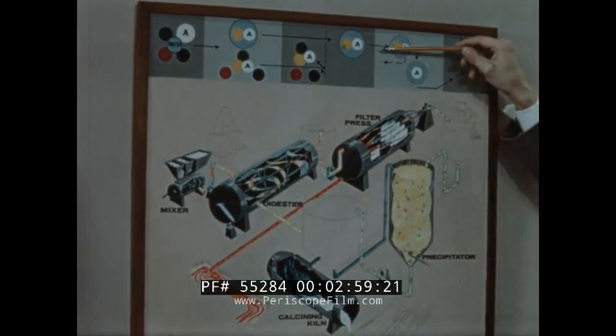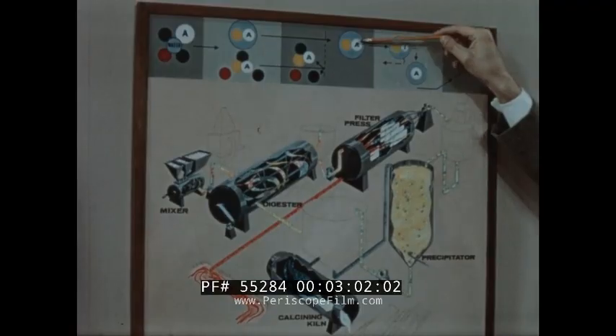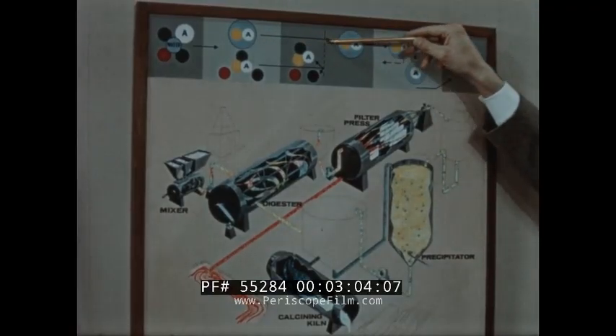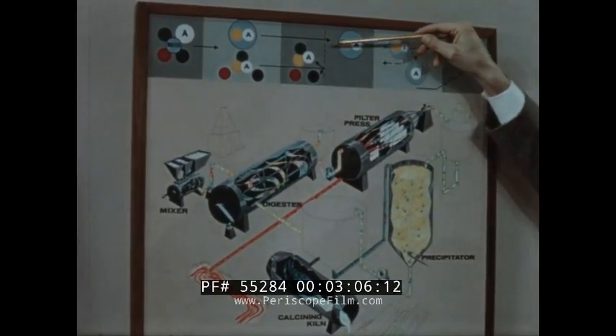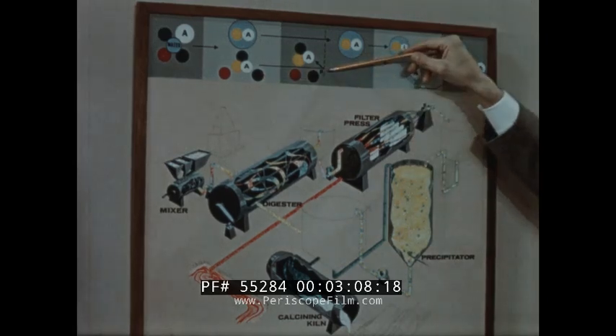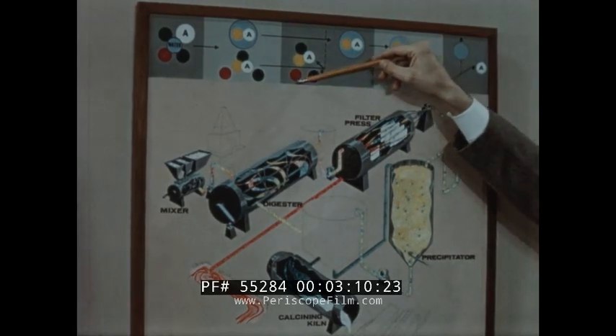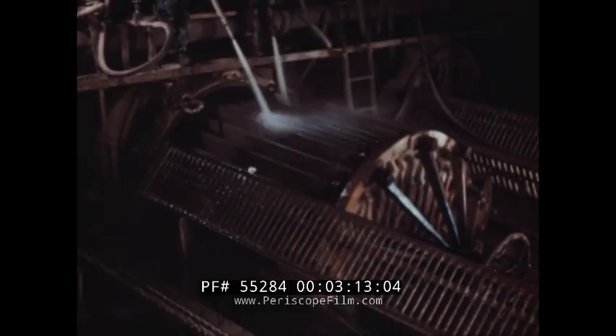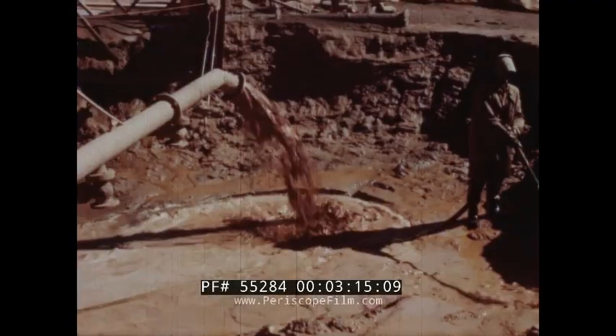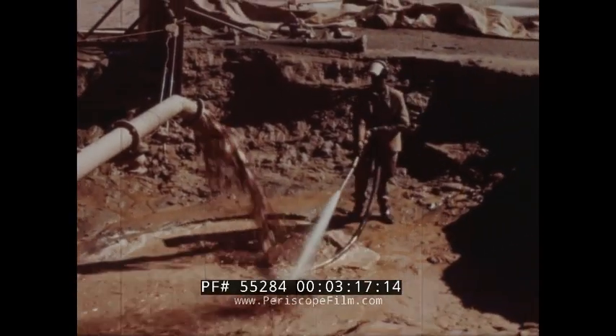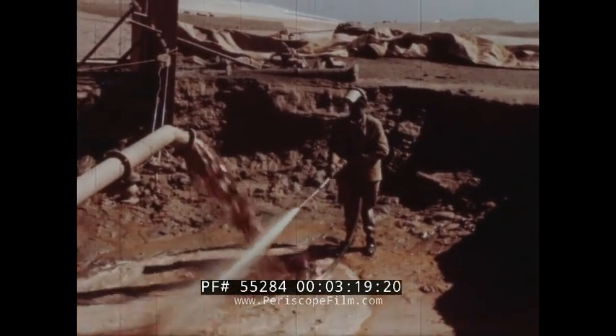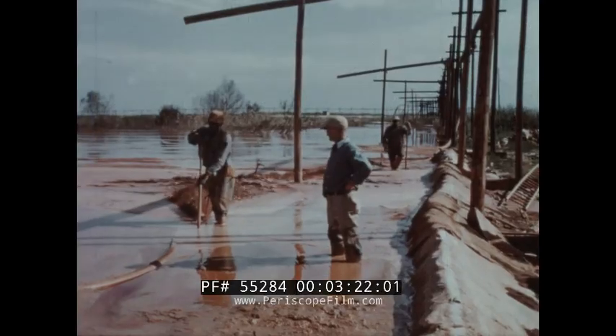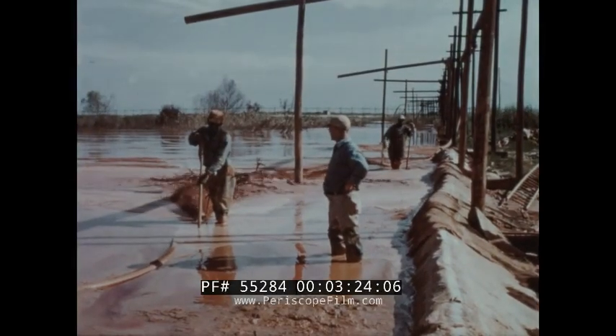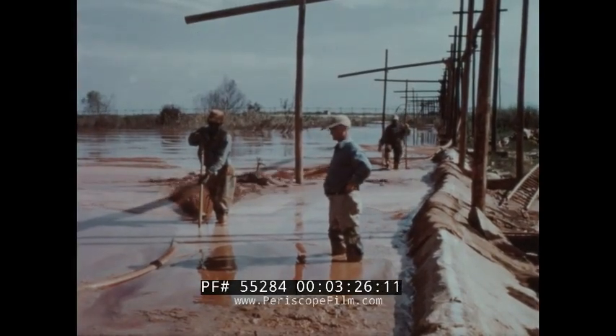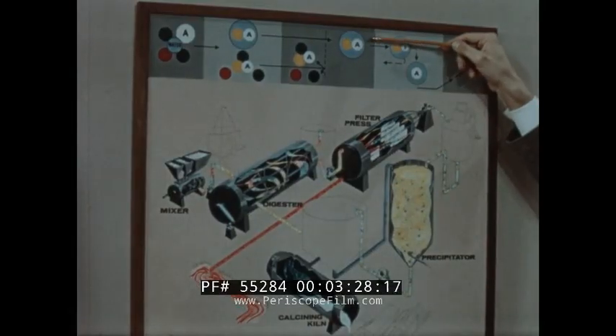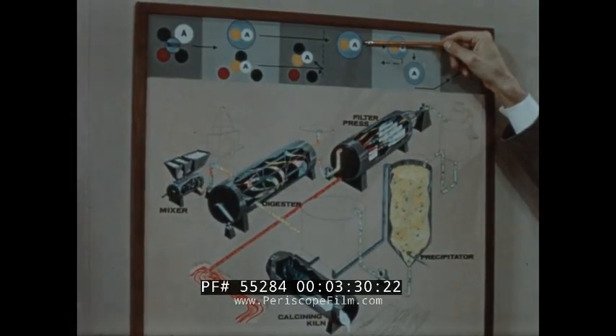Now, the sodium aluminate solution, being a liquid, passes through the cloth, but the solid impurities remain on the surface. And these are washed with jets of water, forming a red mud, which is pumped off as waste. The silica, however, has combined with some of the soda and alumina, which means a loss of some of the alumina. We now have a clean solution of sodium aluminate.